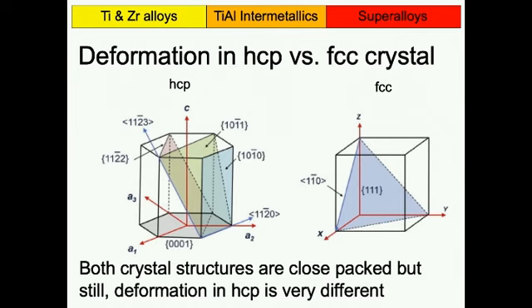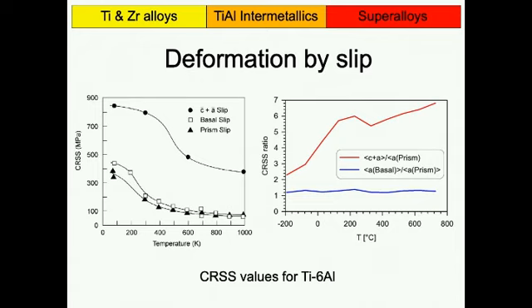So the slip direction of the two easy slip modes is the same and has no C component. The slip mode which has a C component is C plus A slip. This is the critical resolved shear stress as a function of temperature, for titanium in this case. You can see that the critical resolved shear stress, the ease of activating the slip, is much more difficult for C plus A compared to basal or prismatic. Those are close together, but C plus A is somewhere between 2.5 and 6 or 7 times more difficult to activate, depending on the temperature.